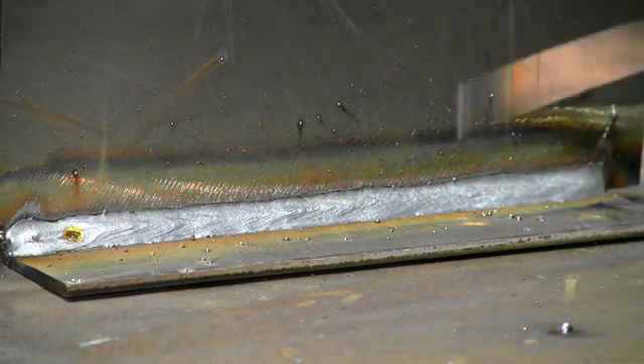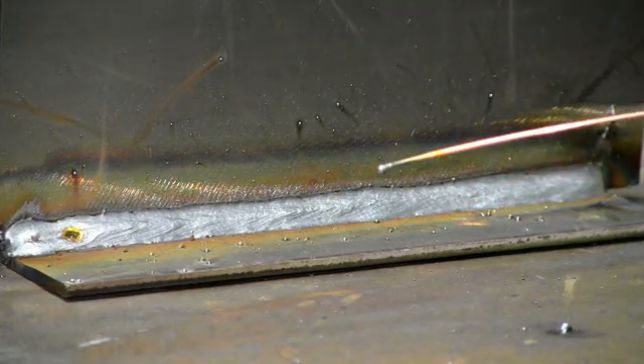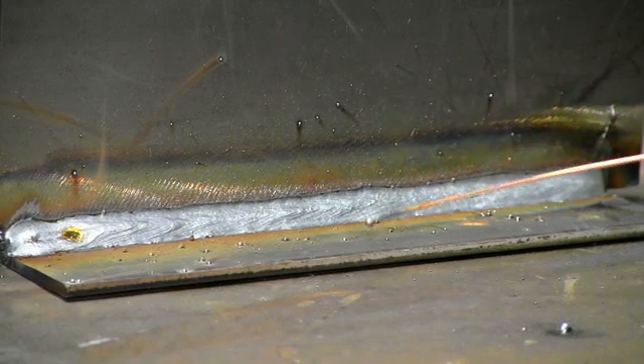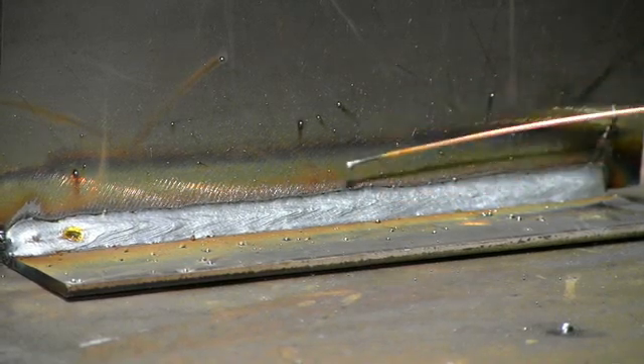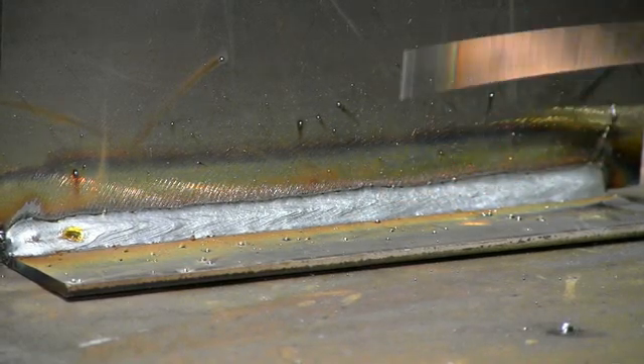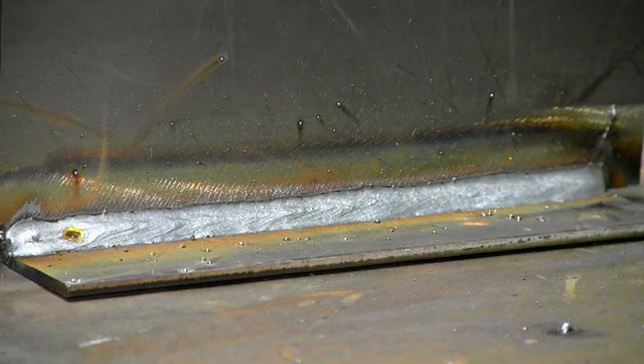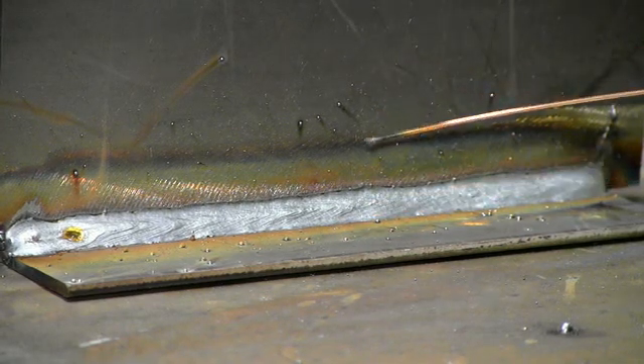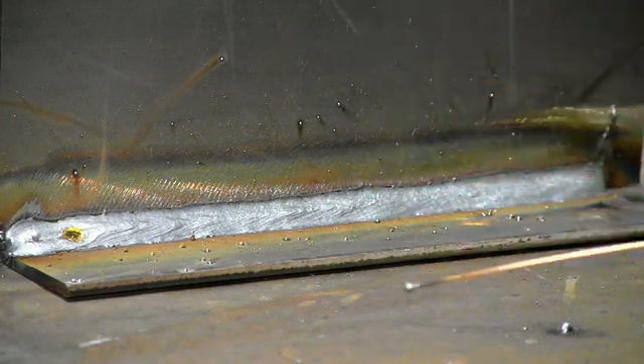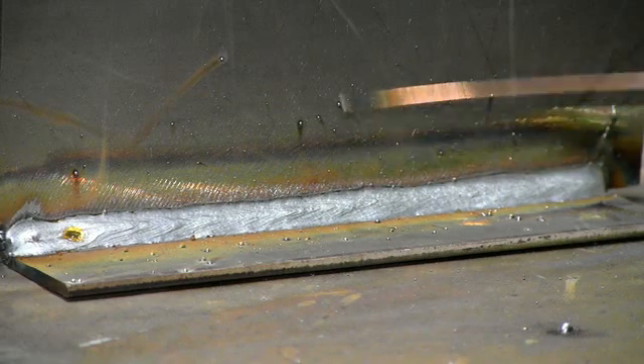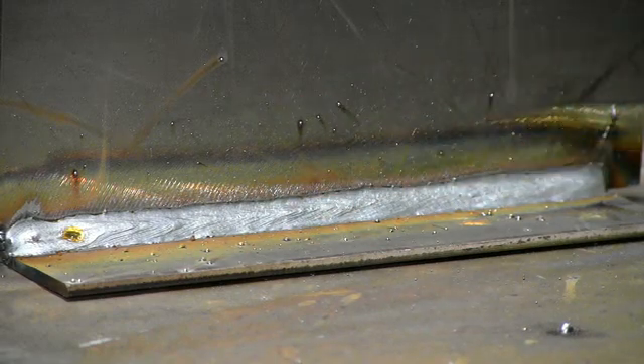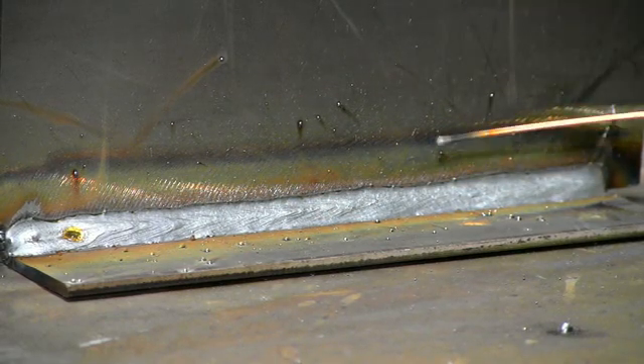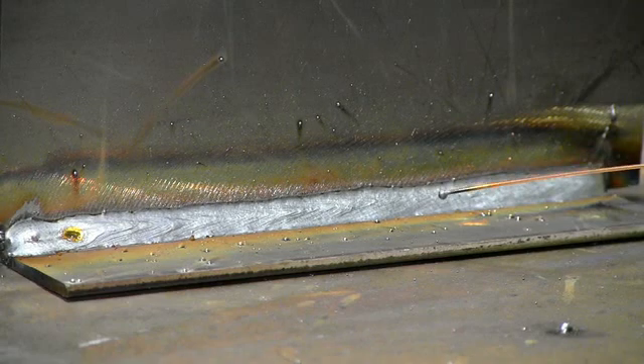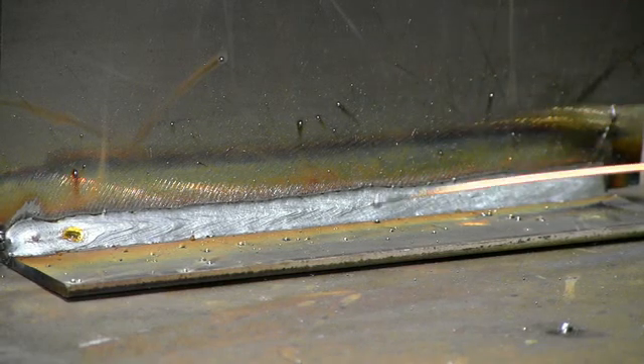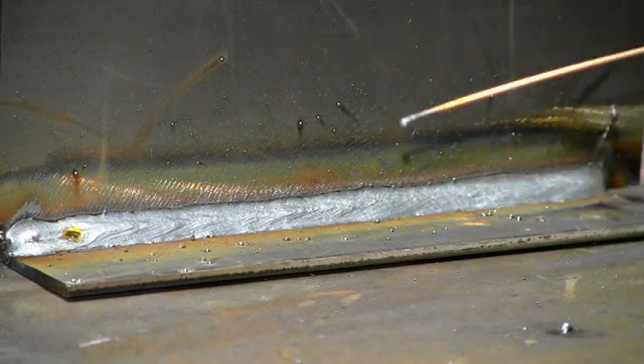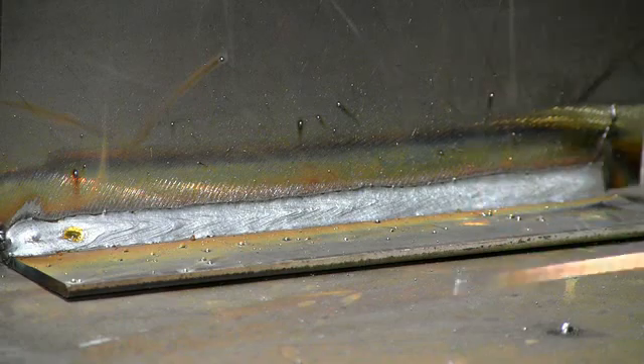Because of that buried arc, it's easier to control the puddle, and you'll find a lot of welders doing this. However, in this case, the wire feed speed was just a little bit too high. They're probably doing that, you know, to try to weld faster. However, if you would just turn the voltage up maybe half of a volt or 1 volt, this spatter would have fixed itself, or brought the wire feed speed down to around 600, and you would have been okay as well. But I hope that gives a good understanding of the balancing act between wire feed speed and voltage.